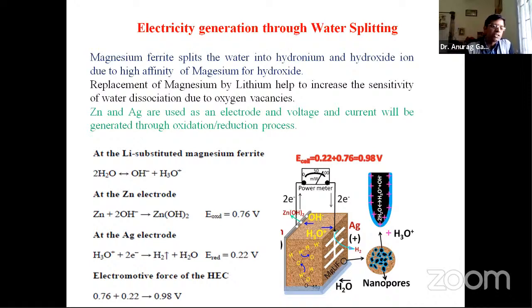There is also another reason to dope the lithium: we are replacing the magnesium by lithium. The magnesium valency is +2 and lithium is +1, so because of that, some oxygen vacancies are created within the material. These oxygen vacancies can also play a role in further improving and sensitizing the water dissociation property of this material, because the material's property is how well we can split the water into hydronium and hydroxide ions. This material is also porous in nature, because we will put the water inside it.